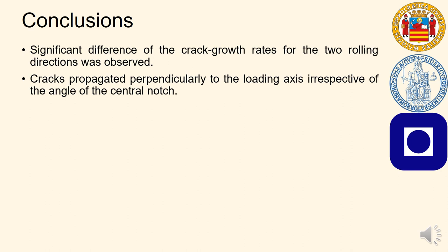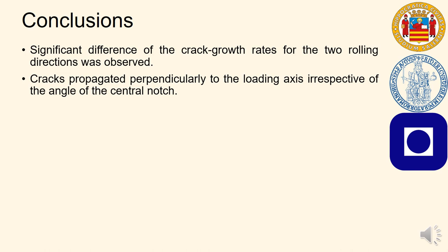To conclude, we are performing an extensive experimental campaign on this aluminum lithium alloy, through uniaxial static fatigue and fracture tests. We observed significant differences in the observations made for the two rolling directions. However, the fracture tests reported that the cracks propagated perpendicularly to the loading axis, irrespective of the angle of the central notch. With reference to the T direction specimens, tests reported that the cracks tended to propagate in between the grains of the material, and also faster than what observed for the L direction. Thank you for your attention.